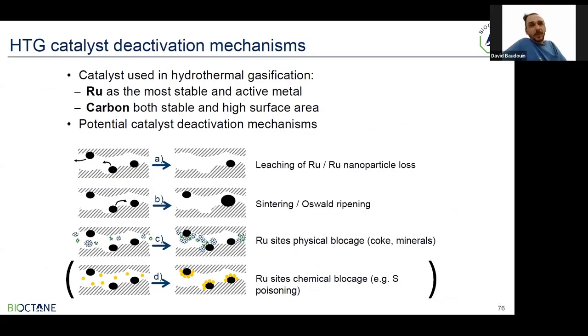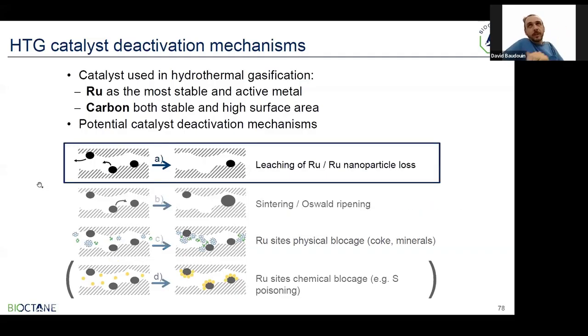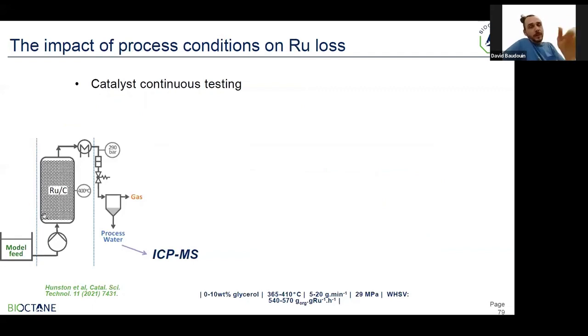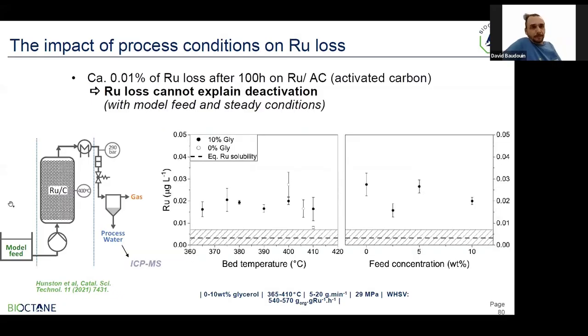So I'll come back to the slide that you have seen before, the different mechanisms that can explain the deactivation. Before moving to the question of coking, I'll just give you a few hints regarding leaching. Next slide, please. So the loss of active metal from our catalyst bed. Next slide. So we use the same setup that I introduced before. We used ICP-MS and not OES, the MS being much more sensitive than the OES detector. Next slide, please.